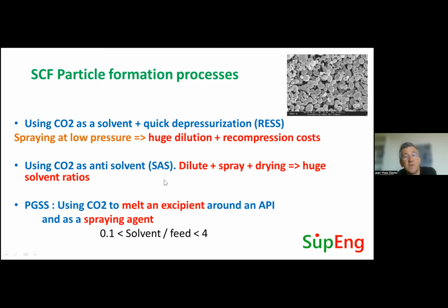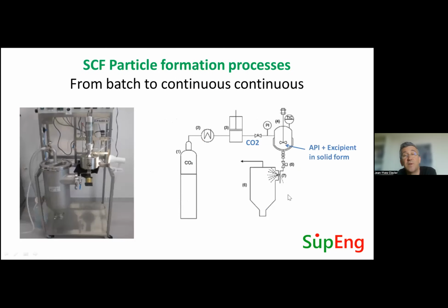The one I want to detail a little bit is what we call PGSS, where you use CO2 to melt an excipient, a polymer usually. So using CO2 allows to decrease melting temperature, and basically you will use a batch reactor where you will melt this polymer. You mix a product to be encapsulated, and you use also CO2 to spray this at high pressure. And here you get a very nice solvent CO2 over feed ratio, and this leads to a nice application.